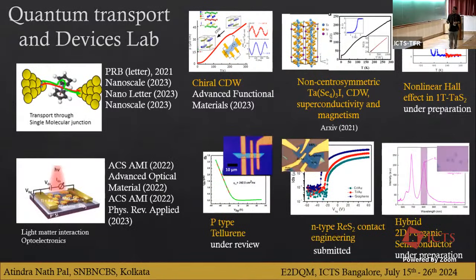Of course, we have a large 2D activity, like engineering 2D materials. We have worked on light matter interaction and optoelectronics in large area 2D-0D hybrid material systems. Then recently we have started working on p-type 2D materials, like contact engineering, understanding the defects and noise in this system, like p-type tellurene, then n-type ReS2. And a very recent direction is engineering 2D organic hybrid materials, where we put organic semiconductors on 2D materials like MoS2, and we are seeing some interesting interlayer exciton or similar observations.